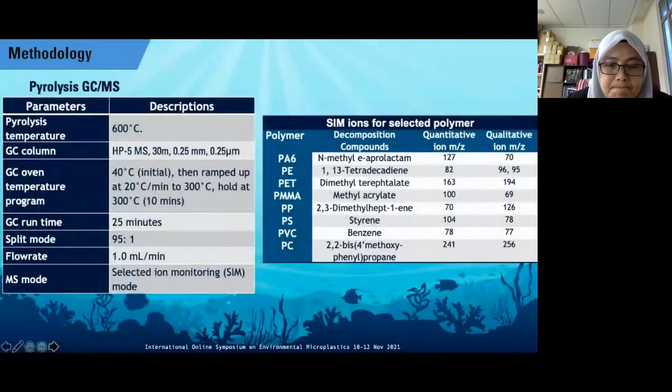And these are the analytical parameters for the pyrolysis program that was used. The pyrolyzer, as I mentioned earlier, is at 600 degrees C for pyrolysis temperature. This pyrolyzer is attached to the GC that is coupled with the MS. For this program, the pyrolysis period is 10 minutes, and the transfer line was heated and maintained at 320 degrees, I think.